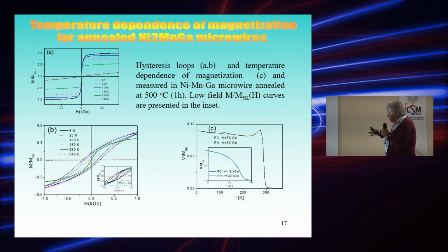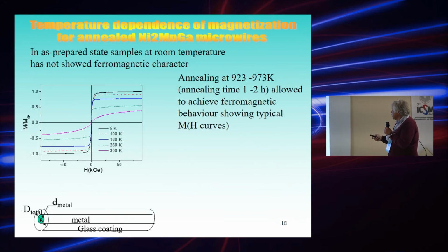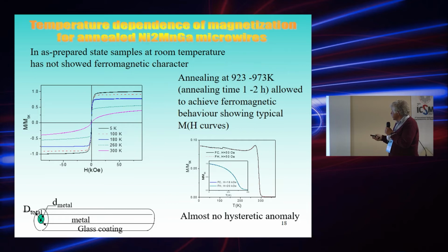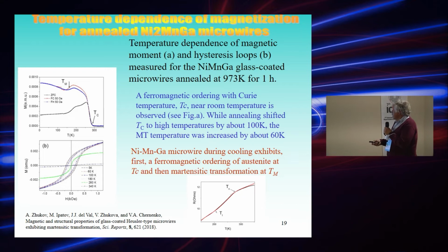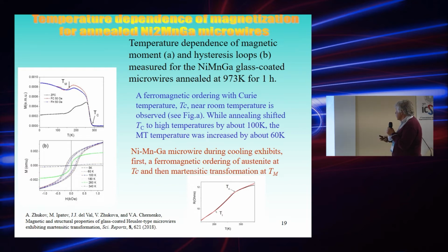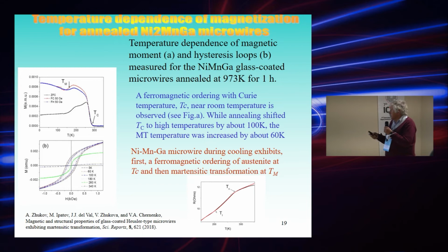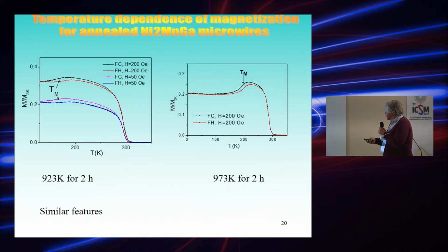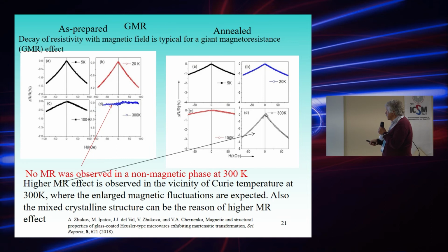In fact, we were trying to vary the annealing conditions and to find the right conditions to achieve the first order transition of this kind of material. This is a typical nickel manganese gallium microwire. Finally, we found the conditions in which we observed this hysteretic behavior and a Curie temperature near room temperature. This means that we achieved conditions, quite recently, in which we realized the possibility to observe magnetocaloric effects, and also this change of magnetic properties which is typical for first order transition of this kind of materials. There are two more annealing conditions in which we observed similar features.